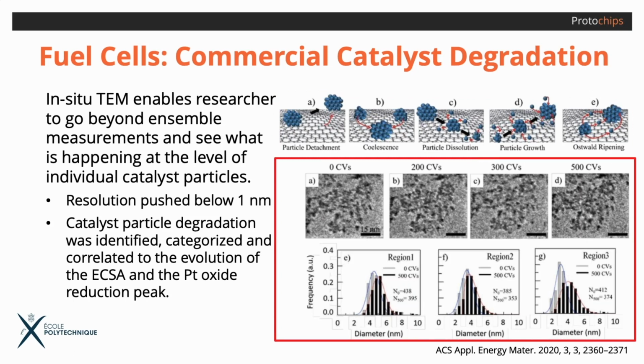Corresponding with the sequential cathodic and anodic shifts observed in the platinum reduction peak, particle sizes measured from the TEM images followed the same pattern. In this case, we see the particles beginning to dissolve and become smaller, and then starting to grow again, following typical Ostwald ripening mechanisms. In situ TEM enabled the researchers to understand on a mechanistic level the structural changes contributing to fuel cell aging and degradation that they were able to also see in the electrochemistry ensemble measurements.